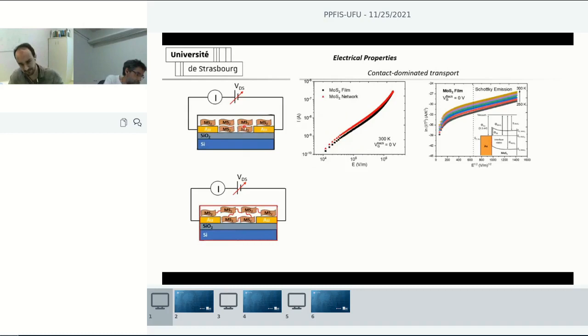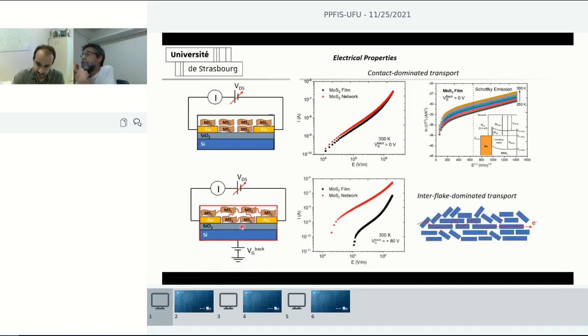This is because here the transport is dominated by the film-contact Schottky barrier. Here we have the typical Schottky plot from which we can extract the barrier height. So what we did to circumvent this is we applied the gate voltage to lower the barrier and to probe the bulk transport properties of film and network.